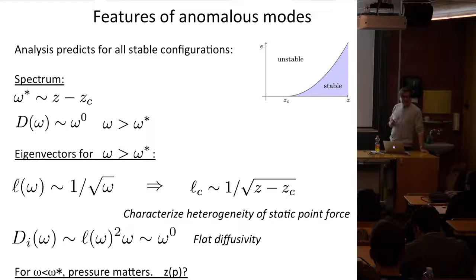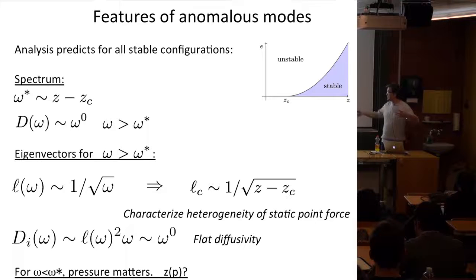And you can also now understand why the diffusivity was flat. So the diffusivity is really a diffusion constant. So you can think of it as a length squared times the frequency, right? So those modes, if you want, they are correlated. They have a characteristic time scale because they have the frequency omega, right? But they have a characteristic length scale on which they are correlated. So how much they transport heat will be related to the square of a length scale divided by a time scale, or times the frequency. And then you understand why it's actually flat.